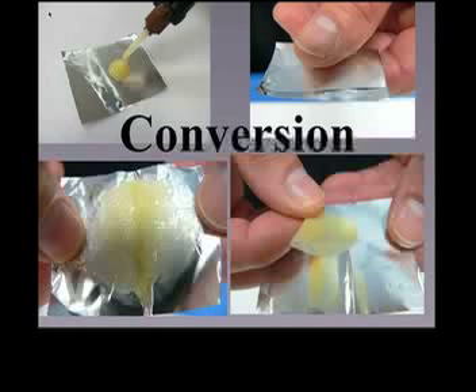It's interesting that Dual Link sets in 5 minutes. Some cements require 10 to 12 minutes, and the cleanup must be delayed so as not to interrupt bond formation, the whole nine yards. So we have to be careful with our compatibility or incompatibility with some of these materials.